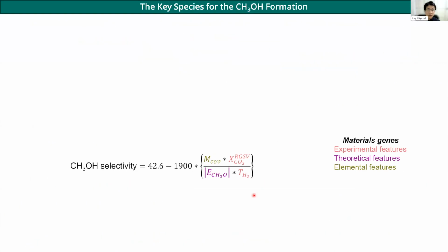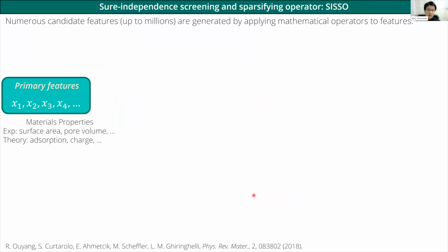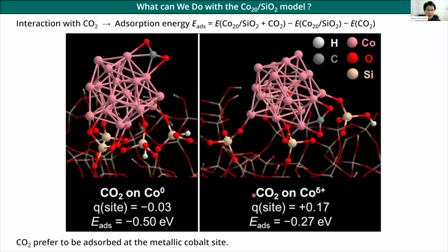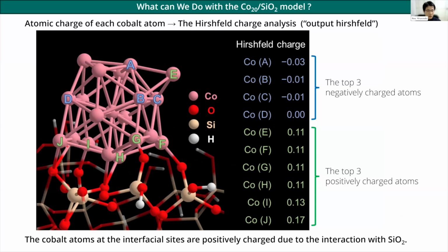Okay, yeah, that's a very good question. Actually, I skipped this part. I picked the most planar side of the metal cluster, and that is the reason why: the interaction between the metal cluster and the support material is stabilized by interaction with oxygen atoms. I'd like to maximize this interaction, so I picked the most planar and largest facet of the cluster when it interacts with the silica slab. I hope this answers the question.